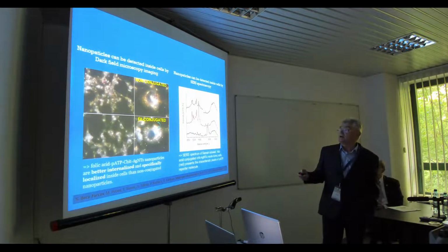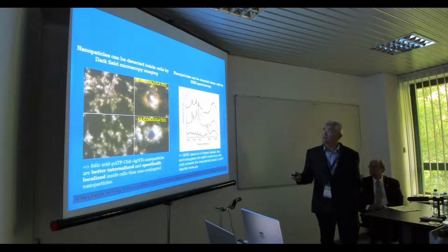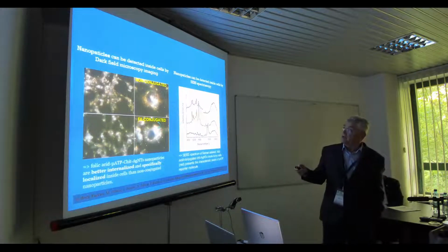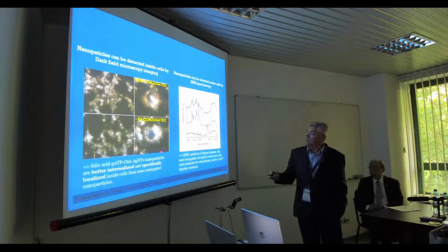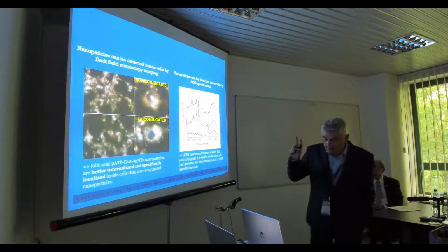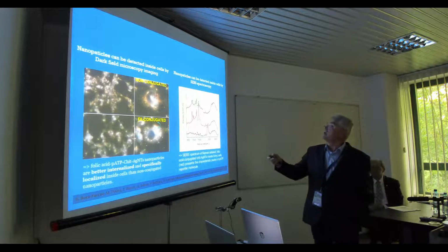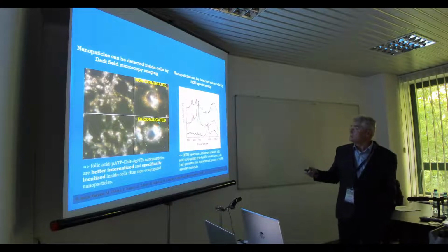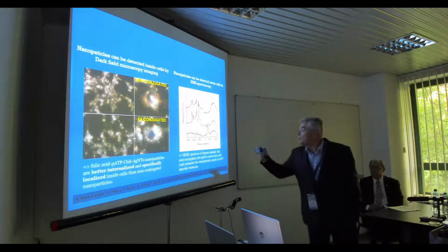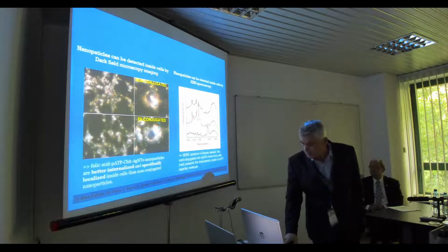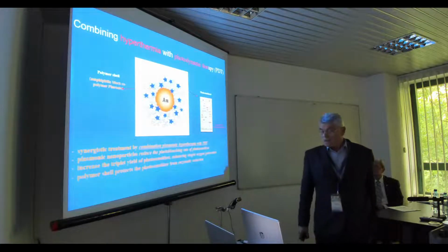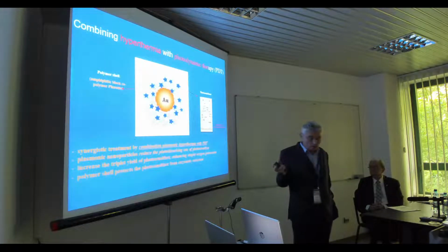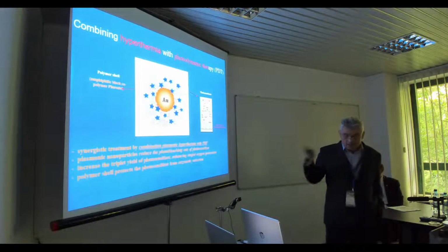And here also some dark field experiments where you can prove that by conjugation with folic acid there is a much higher density of nanoparticles localized on the membrane of the cell relative to non-conjugated with folic acid. And also the specific band helps us to recognize the position in the cell. Now this was a single therapy, hyperthermia, targeted and not targeted.